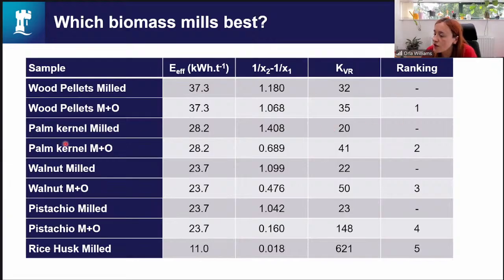So for instance, if we only looked at the milled product, we can see that palm kernel material came out best, with walnut second, then pistachio. They're all in the low 20s, and the wood pellets are up at 32. However, when we look at the milled plus the overflow, suddenly wood pellets has gone right to the front and pistachio is down at 148. So it's shown a very different performance to the others. Now, rice husk had a very poor result because it has a very low energy, but it didn't really change in size, which shows it actually didn't really need milling.